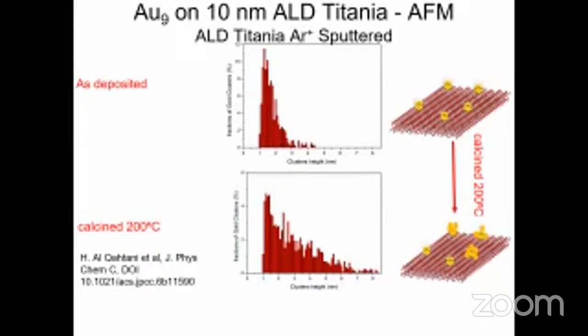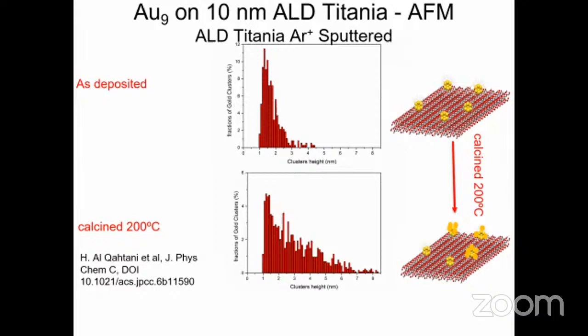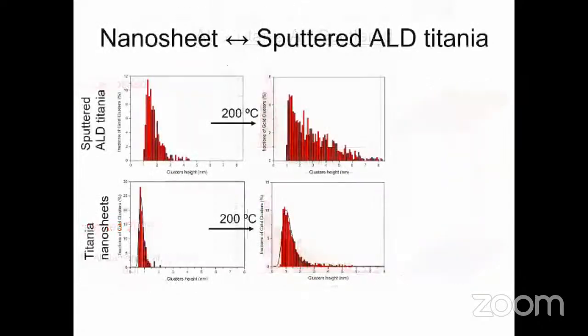And we sputter this kind, create what's called the oxygen defects. And this is on the substrate and to reduce the aggregation itself. But even though we have some aggregation of this gold nine cluster, and this is what's showing on the histogram, because the size is increasing, the tail is increasing actually. And this is like two different methodologies.